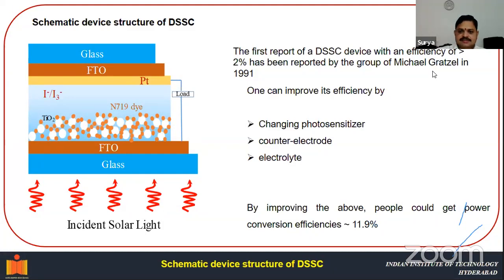The Gratzel solar cells. One can also improve their efficiencies. Although efficiencies of 2% have been reported, people have been able to improve the efficiencies of the solar cells by changing the photosensitizer like the dye, the counter electrodes, the kind of electrodes that we use, and the electrolyte. Here we use I minus, I3 minus. One can also replace this electrolyte with other electrolytes.